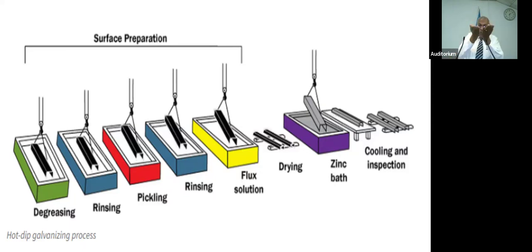After you bend it into four sides, one side you are welding. That zinc is burnt off. Then they use ZRC and put a small strip and cover it. Inside, how are they going to take ZRC and spray it? Outside, you and I can take a spray and spray it, no? But inside, how are you going to send a person with a spray can? That means it is not treated at all. So you have to really understand that in pre-galvanized square tubes, there is one line inside which is not treated.